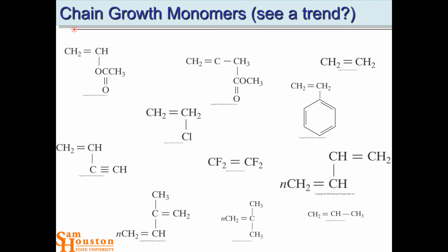And so they knew the material was still in there, but it was no longer in the gas phase. And so then the story goes, they cut open the cylinder, and they found that the tetrafluoroethylene had polymerized to make Teflon in that tank. And so it might have been exothermic, they just didn't notice. The tank may have heated up. In fact, that can be very dangerous. Like I was saying about acetylene, you have to dissolve acetylene in acetone inside the tank so that it doesn't polymerize and make an exothermic bomb.